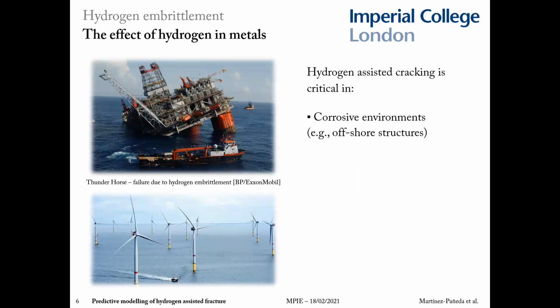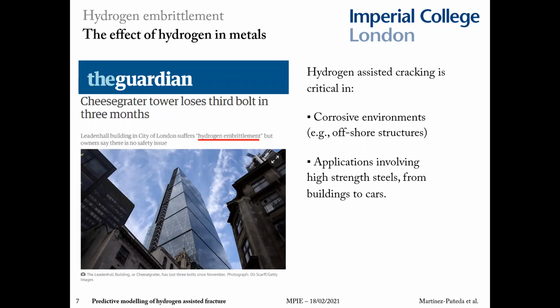So before high strength steels were developed, hydrogen embrittlement was mostly a problem related to aggressive environments, for example, those typical of offshore structures in the energy industry. However, high strength steels are very cost effective and we want to use them for our buildings, bridges, railways, cars. And this is triggering numerous hydrogen fracture problems across the defense, transport, and construction sectors. And in otherwise benign environments, you can see an example in this newspaper article where hydrogen embrittlement is bringing structural integrity problems to one of the most famous skyscrapers in London.